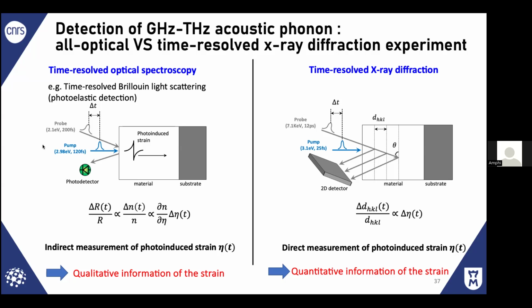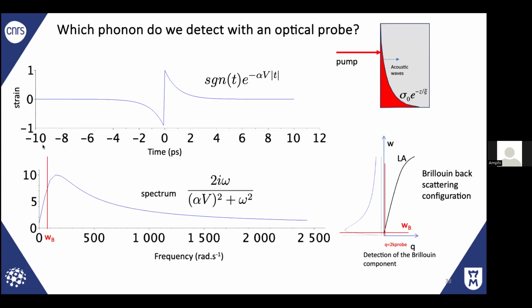For X-ray, by using the Bragg law, you can immediately measure how the lattice distance and interatomic distance change, by recording the interatomic distance with Bragg law X-ray diffraction. So I will also show you one example about that. So let me come back to the phonon spectrum. This is what you can emit with light.